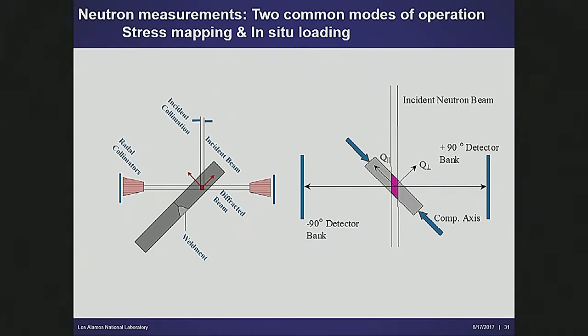So now let me spin over some instrumentation, and then I'll get to the 2 examples that I want to talk about, probably more interesting to you. First approximation, for neutron measurements, there are sort of 2 modes, spatially resolved. At a spallation neutron source, you do it with radial collimators. At a reactor source, you typically use apertures pushed up close to the sample. Both facilities frequently support measurements with load frames. There's lots of science that you can do by putting a known load on there.